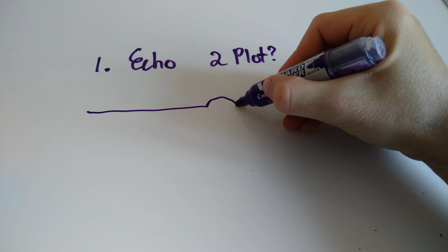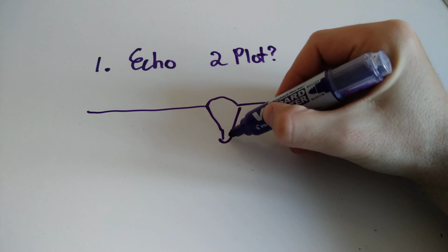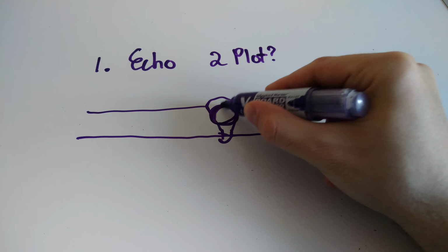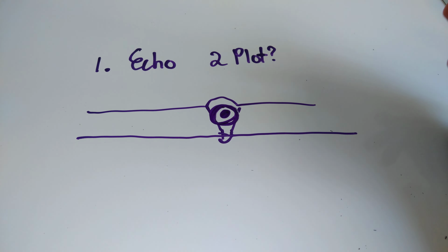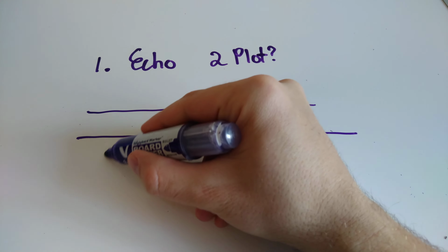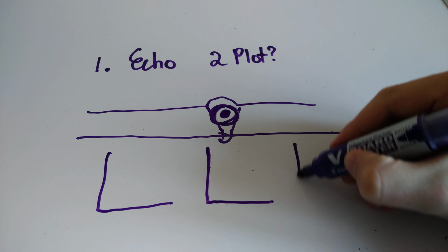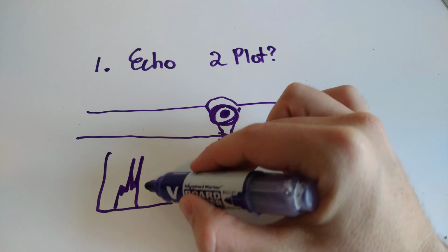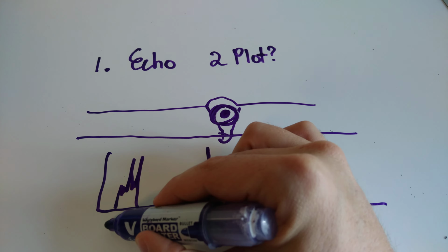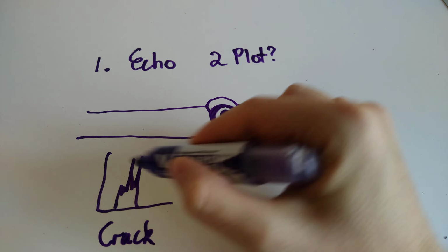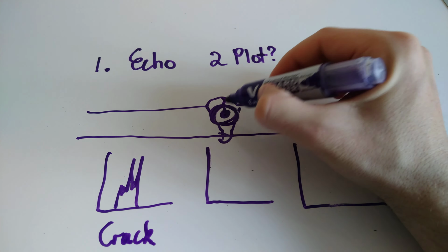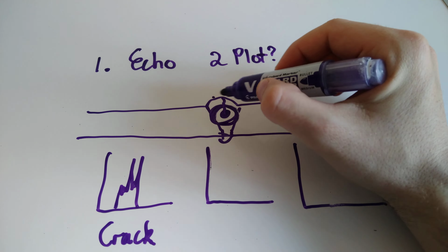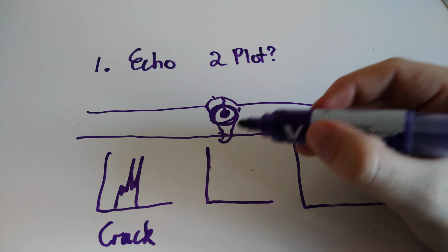So let's do another one. Once again, nice single V weld, expertly drawn. And let's say the indication plots out somewhere there, in this area. Now I know from a weld there are a few indications that are likely to come up here, and I generally break it down into 3. Once again, we might have something similar, a high echo with a little bit wider, a high amplitude, and it's got a couple of peaks. This could be something like a centerline crack or a crack in the middle of the weld. You'll typically find that this starts at the surface. So if you do a surface technique like dye penetrant or magnetic particle, you could detect this as well, just to support your ultrasonic testing.